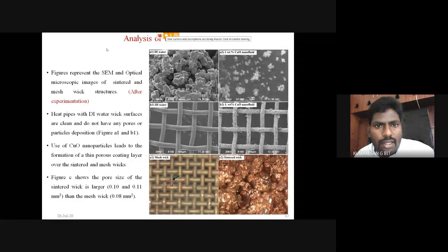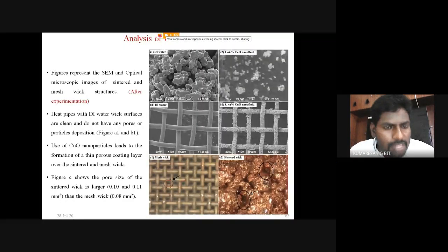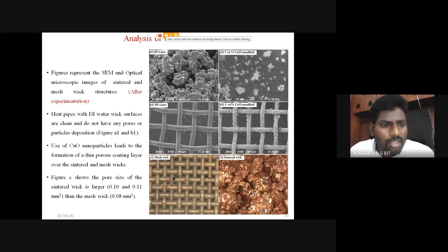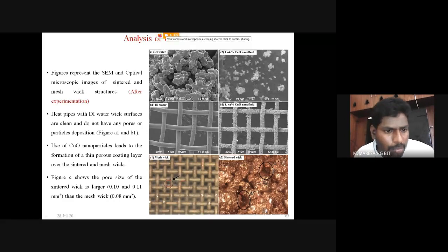Okay. Then this one is the analysis of wick structure for mesh and sintered wicks. The figure represents the SEM and the optical microscope images of sintered and mesh wick structures. Then for heat pipes with the DI water, wick surfaces are clean and do not have any pores or particle deposition over the surface.